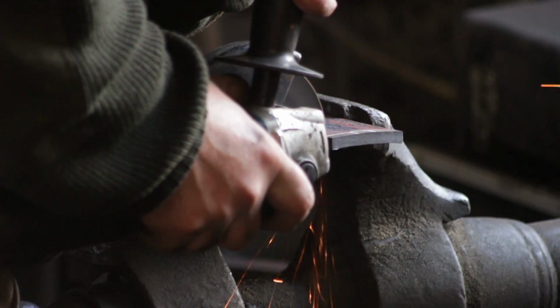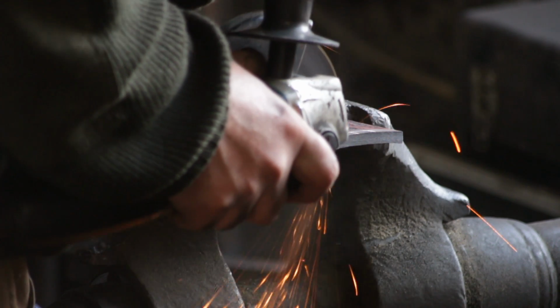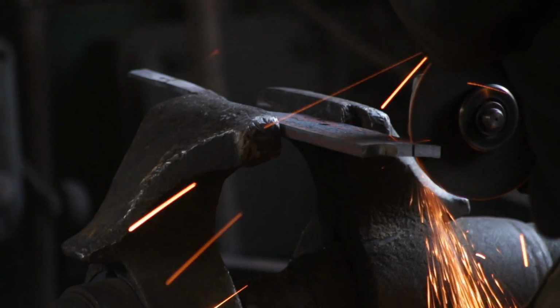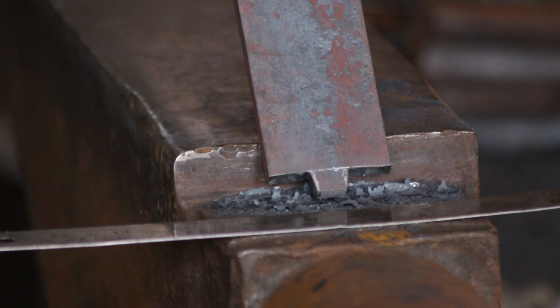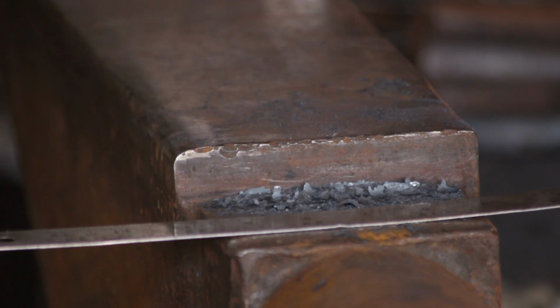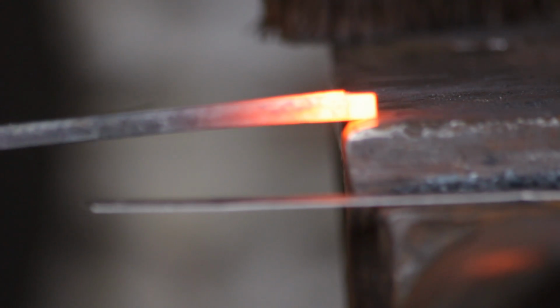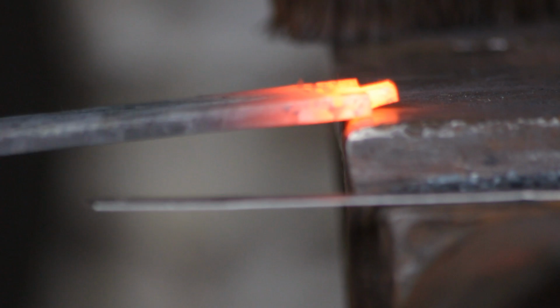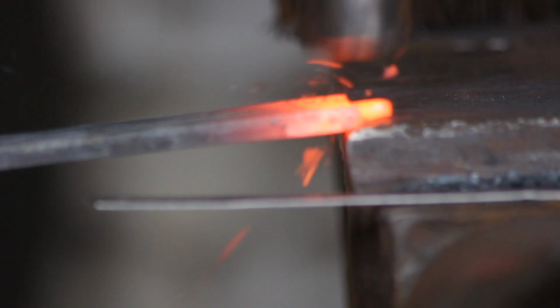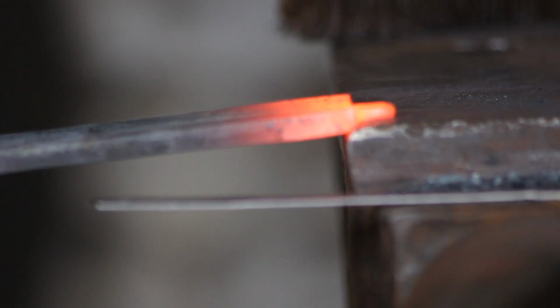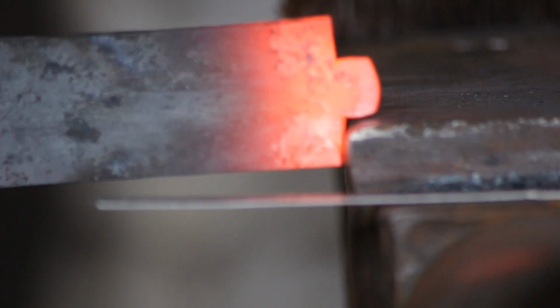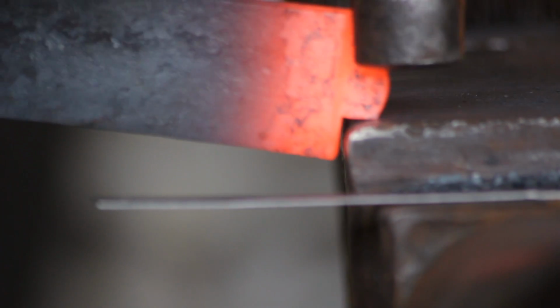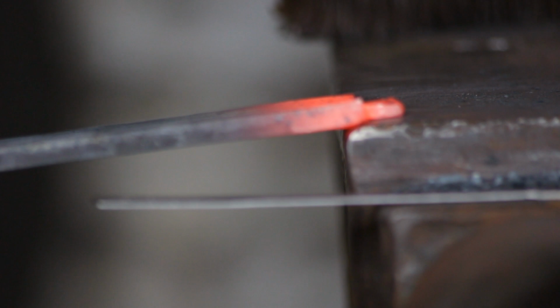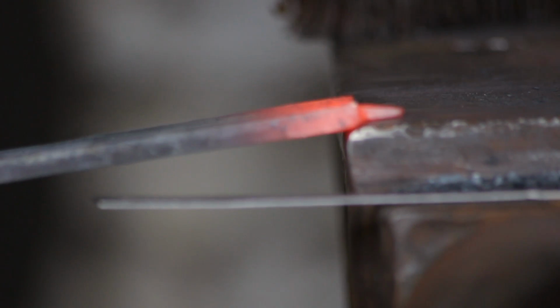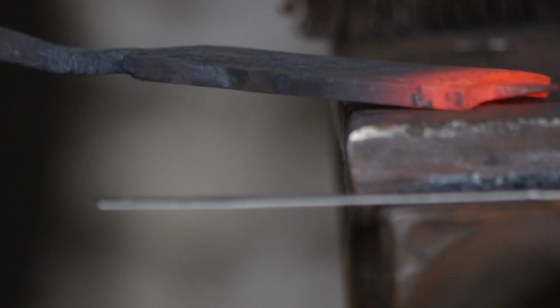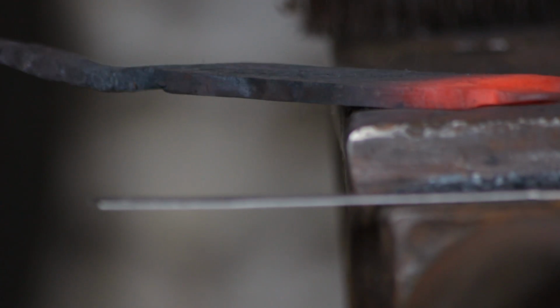Now this tab will come up behind the bayonet tang and will support the scarf there, and that will allow me to close that up where otherwise I might end up with a gall. So in order to do this, I will do a set down on this tab. I'm using the radius section of the anvil for this because I don't want to create any galling when I fold it over in a second. I'm just forging that out to a square taper. I'll bring it down to a reasonably fine point so that I don't create again any shearing planes rather than welding planes. So then just give it a tap over,